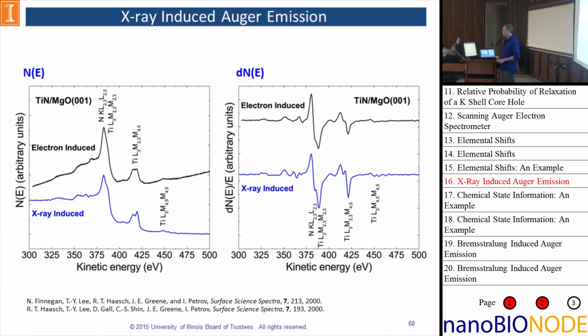Okay, here's a couple of examples of Auger. And these lines, I'm comparing Auger signal that was produced by the electron beam. And if you remember my survey spectra at the beginning, we can also create Auger lines with an X-ray photon. And as you can see, the lines look about the same, which you'd expect because the physics is the same, only the exciting particle is different.